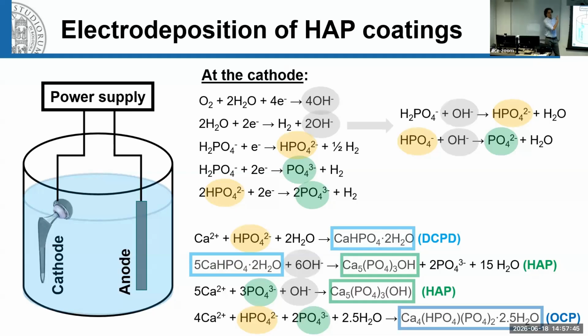Here is when the electrodeposition comes in. Of course, we are not going through all the reactions. The idea is to form hydroxyapatite over the titanium implant. You make it work as the cathode in a system. I don't know how familiar you are with the electrochemistry, but the idea is I place my implant in a bath containing a phosphate salt, the same DAP that we saw. I connect it to an anode and then I apply current. Through several reactions, by making this work at the cathode, it's possible to have formation of a thin layer of hydroxyapatite on the surface of the implant.